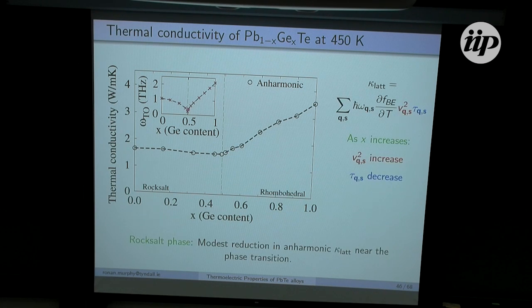And to talk about this, I'll bring back the formula for the lattice thermoconductivity, and just specifically draw your attention to the square of the group velocities and the tau, which are maybe the two main contributions to the lattice thermoconductivity. So if we just focus on the rock salt side of the phase transition for the moment, 0 is lead telluride, and if we imagine increasing the germanium content, we get nearer the phase transition, as I've been discussing, and our phonon lifetimes reduce, as I showed you previously.